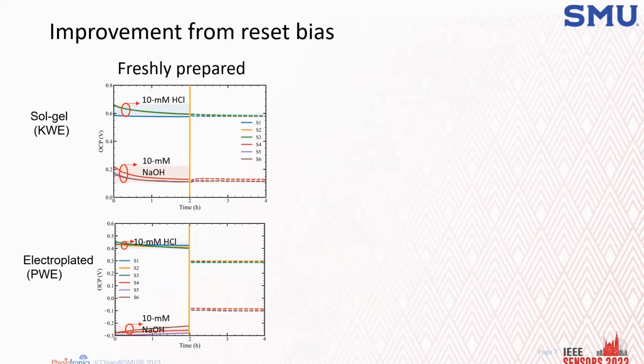For sol-gel and electroplated, we use freshly prepared electrode. That means they have not touched any solution. And we prepare 3 electrodes so we can observe the uniformity of the device, 3 for acid and 3 for alkaline. First, they got tested, and you can see there's a drift problem for all 6 of them. However, then we applied reset at 0.3 volts for acid and 0.28 for alkaline. We found the potential settle very quickly. Within 2 seconds, they are flat.